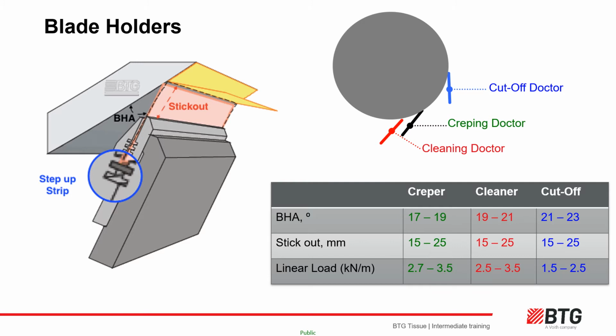Each blade holder will have a pressure gauge on the pistons which push the blade holder to the Yankee cylinder. Some rigid holders rely on this pressure to apply the linear blade load. Most these days have a gel, an air or an oil-filled tube running along the length of the tip of the blade holder to ensure that pressure is evened out along this, or that even the final loading pressure applied here. Having an even profile across the full width of the machine is essential.